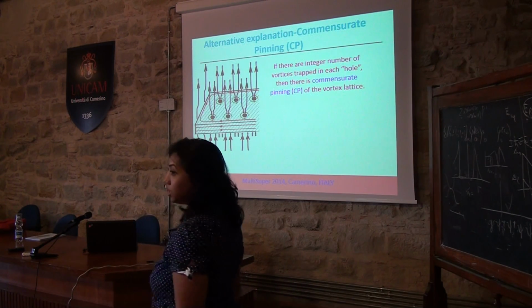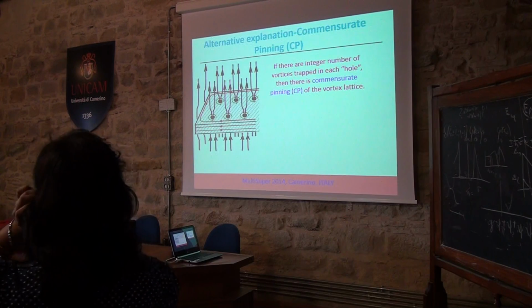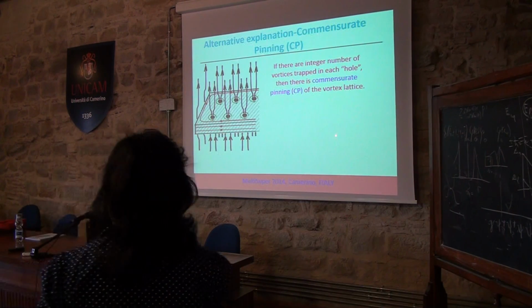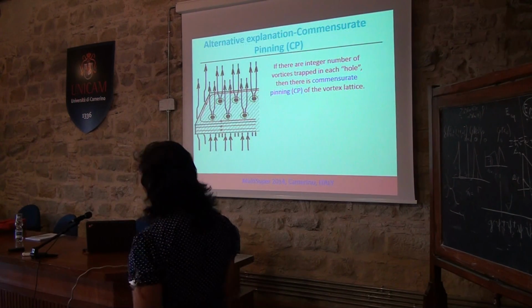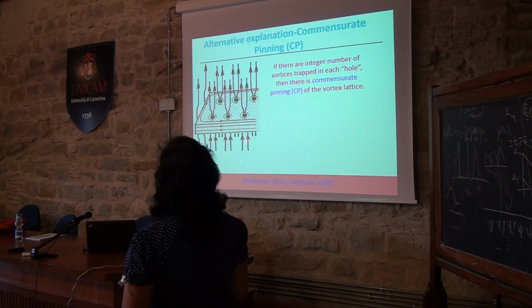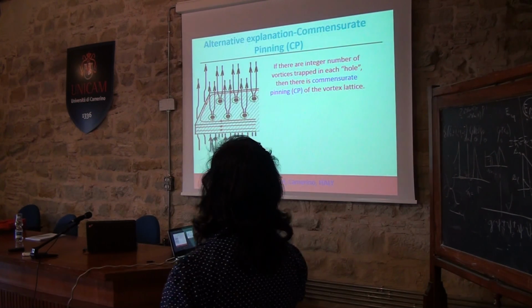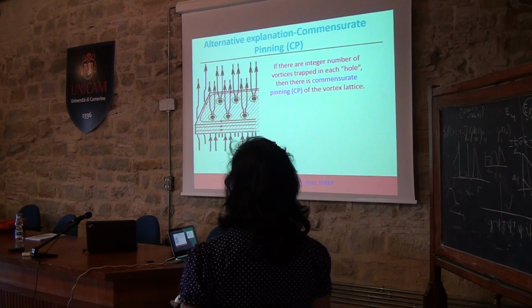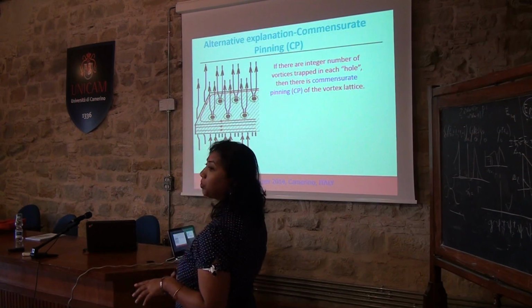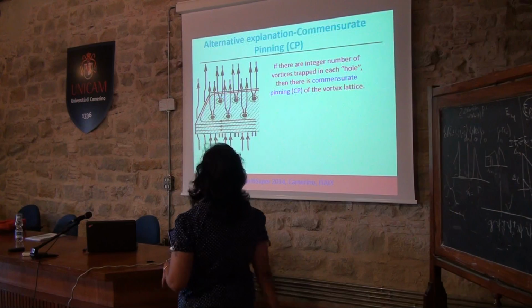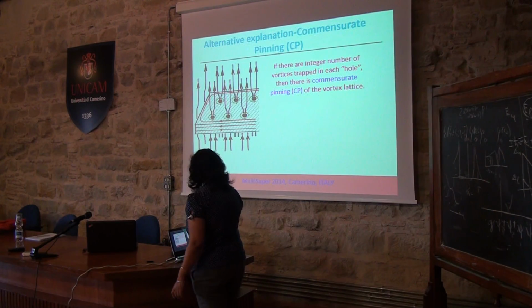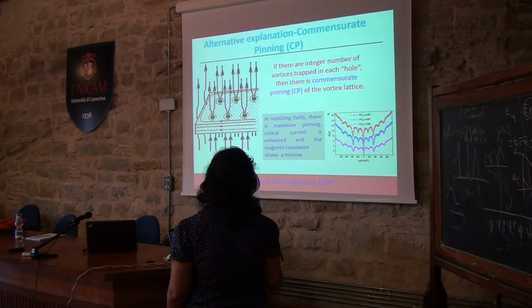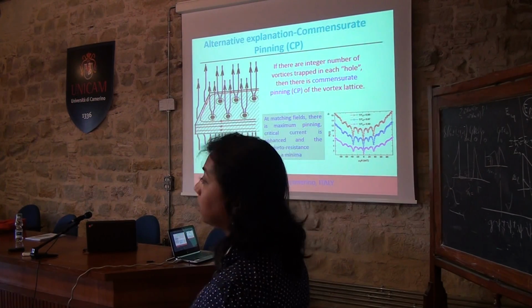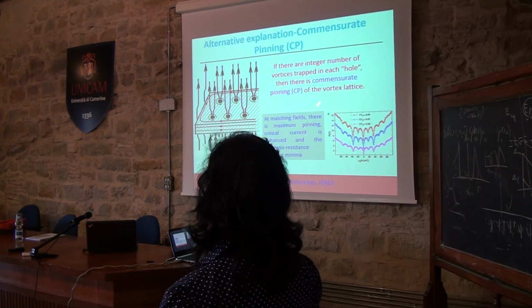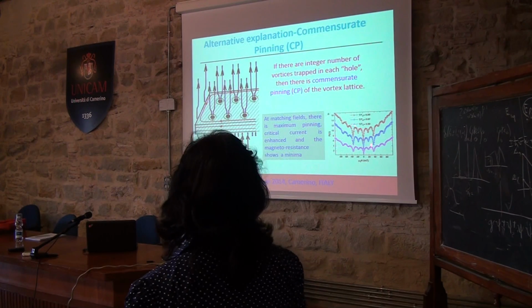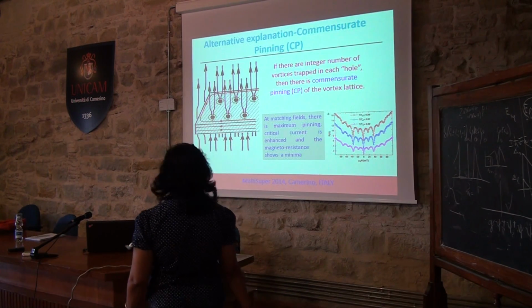So an alternative explanation was given for this kind of system, and the explanation comes from commensurate pinning. It was said that when an integer number of vortices gets trapped in each of these holes, the vortex lattice becomes commensurate with the underlying antidot lattice, and then you start getting matching effects. At the matching fields, there is maximum pinning, so your critical currents will be enhanced, and hence the magnetoresistance will show a minimum.